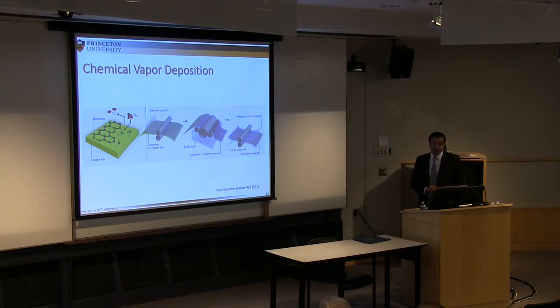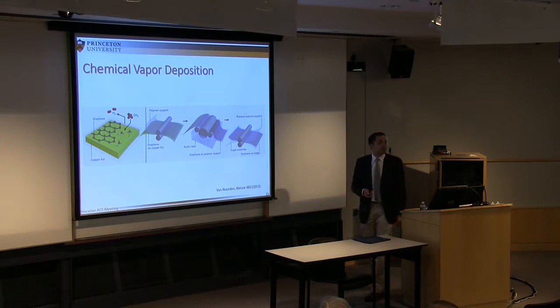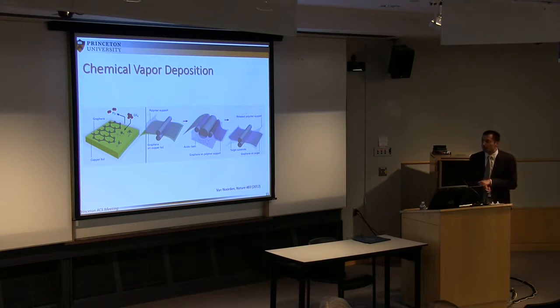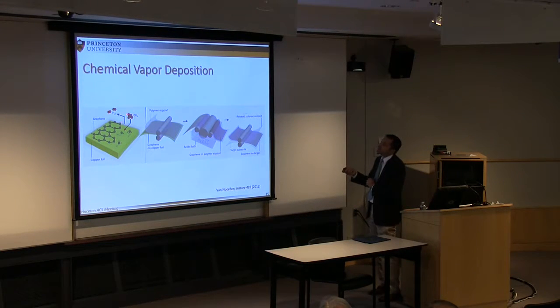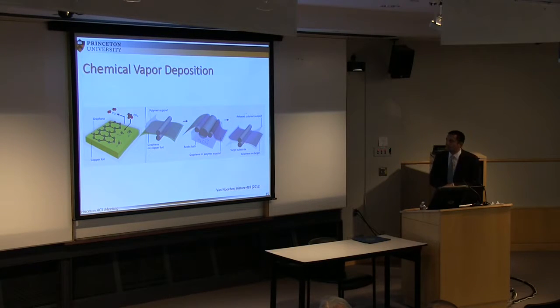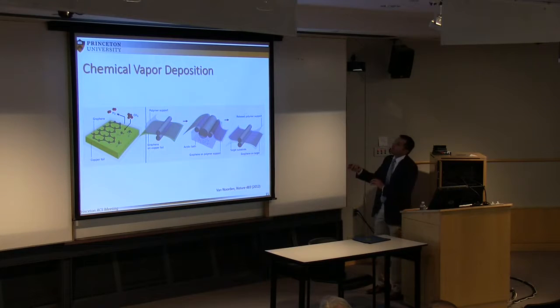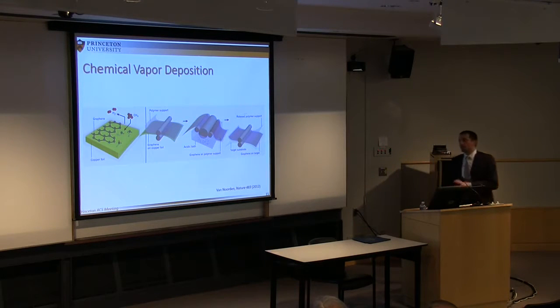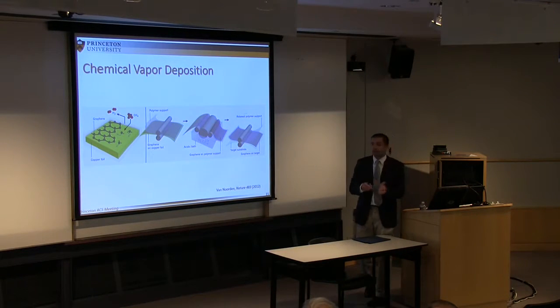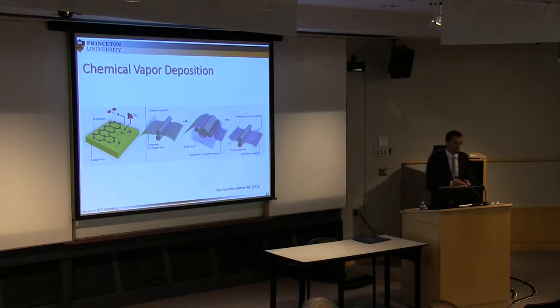So let's start with the CVD. CVD, chemical vapor deposition, consists of having a substrate. As you have seen in the case of nanotubes, we had silica, a non-reactive substrate, stable at high temperatures. Here we use copper because it's highly reactive, and so when you bring this material to roughly 1000 degrees C, and you inject a carbon source such as methane in the presence of carrier gases and in an inert atmosphere, you start breaking the structure and forming the hexagonal structure of graphene. This is, again, a perfectly defect-free graphene, just like the one obtained directly from graphite. And then what do you do with this? That's the problem. You have a substrate now, it's a metal. You can't handle graphene directly.